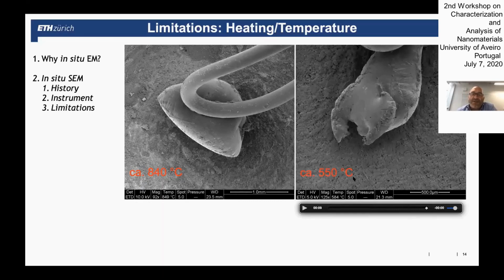So you see, depending on how precisely you locate your thermocouple and how good the mechanical contact is between the sample and the thermocouple, you can create very different temperature readings. So when you want to be accurate, the precise measurement of a temperature is not trivial. Here you see the actual melting point is at around 660, so we got quite huge deviations. So these are two limitations, but still it's a friendly instrument, and it works very nicely.